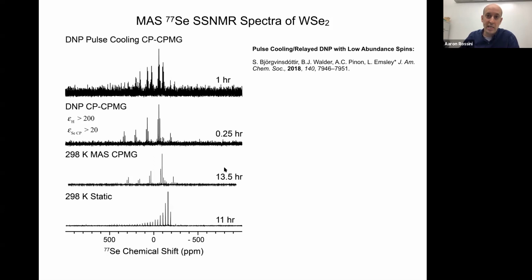So we just took the tungsten selenide, impregnated it with TEKPol in TCE, and did some DNP experiments. We got proton enhancements of over 200, and we estimate that the selenium cross-polarization DNP enhancements are greater than 20. So this means we can now get a magic angle spinning spectrum in about 15 minutes rather than 14 hours.